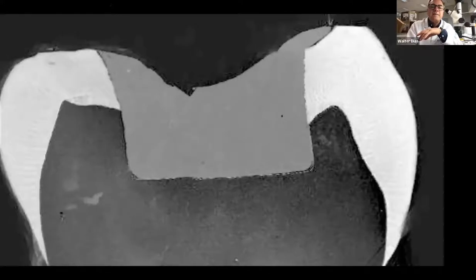And so if we magnify into this area, I go back here and I show it right here. If we magnify, we see here the composite, we see the adhesive, we see the enamel rods. And what you see here is the cohesive fracture within the enamel rods that were displaced by the adhesive. Okay, so that's why I think we should always finish the margins in slow speed when we're preparing.